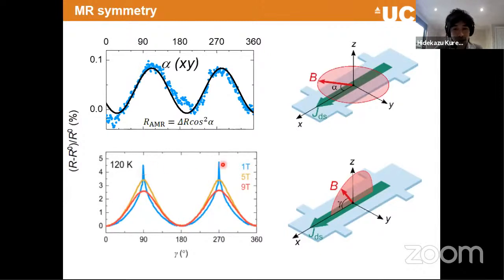And on top of it, when we apply a large magnetic field, like 9 Tesla, it becomes almost more sinusoidal compared to the one we get at 1 Tesla. And this value is already much bigger than our magnetic anisotropy. Therefore, it's something to do with the transport, which is very strange, and probably strongly related to the dimensionality of this material. We don't know what the origin of this is, but I just want to share because some of you can probably give us some idea of how to explain it.